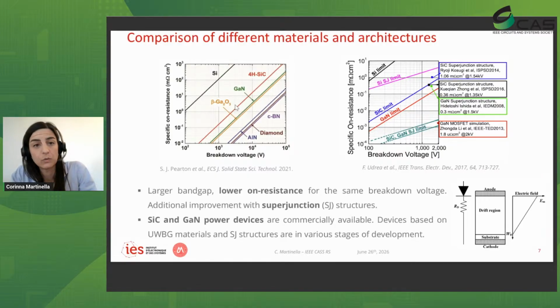A second way to improve it is to change the architecture of the component and use a superjunction design. So we can see here the limit of silicon devices. When moving to superjunction devices, the slope of this line changes. And again, things will get even more interesting when we will be able to produce silicon carbide superjunction devices. In fact, these days, superjunctions are only available for silicon components, but they are at different stages of development for silicon carbide.